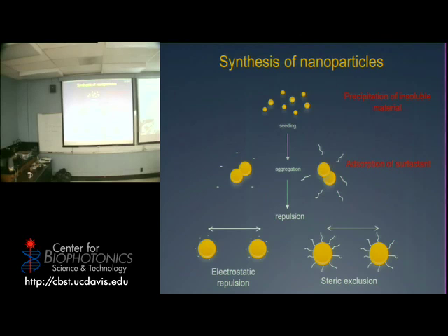If you take another common material like cadmium selenide, for example, you do the same thing. You start from a cadmium precursor, typically an organometallic complex, and you heat it up very hot, and you start decomposing it. If you're in the presence of a selenide source or a sulfide source, depending on the quantum dot you're trying to make, you form these seedlings. So you can play with temperature, concentration, surfactants, time, order of addition, and all these things define the properties.